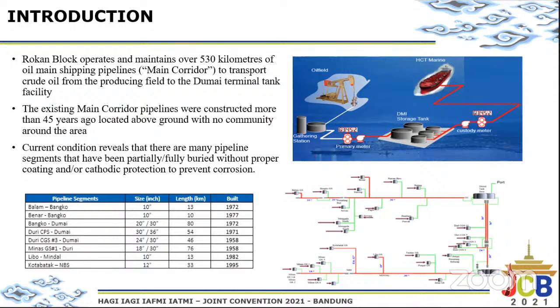The existing main corridor pipelines were constructed more than 45 years ago, located above ground with no community around the area. But the current condition reveals that there are many pipeline segments that are partially or fully buried without proper coating and cathodic protection to prevent corrosion. As shown in the slide, the table shows there are 8 segments of main corridors, and the picture shows the schematic diagram of the Rokan Block main corridor pipeline.